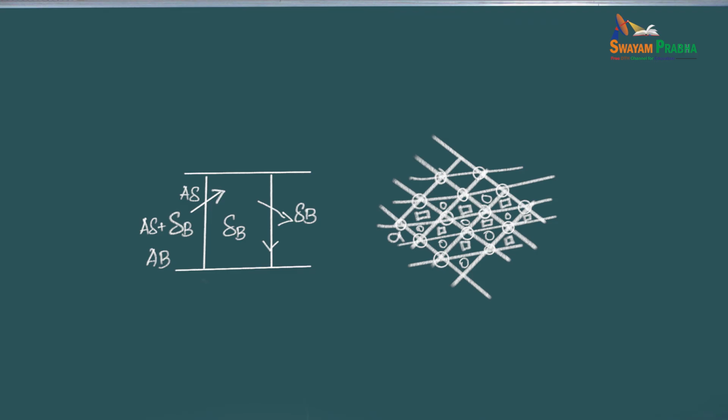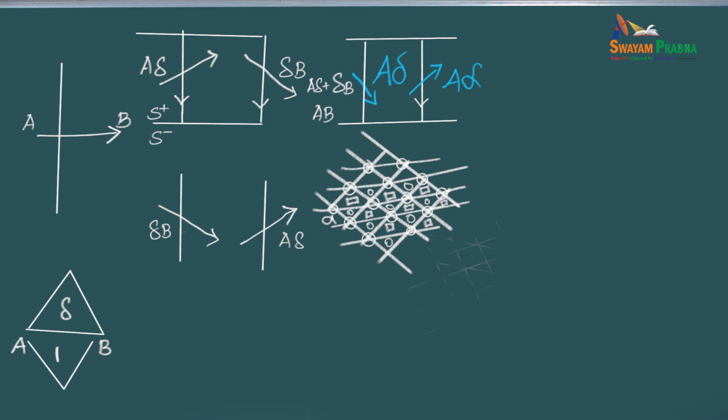What you have done is this: if this is the A plane and this was the B plane, by shifting like this you have transformed the B plane into an A plane. So your stacking is going to be A, B, C, A, B, C, and that's not the stacking fault. Now, if we do the inverse, we do this.